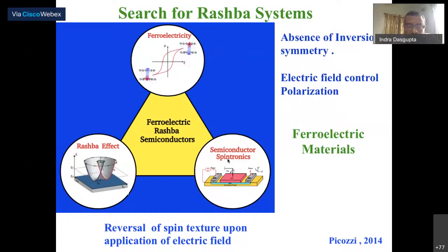The most important thing is that upon application of an electric field, you can essentially reverse the electric polarization, or ferroelectric polarization. So if the Rashba effect could be realized in such a system, then upon an application of electric field, you can essentially reverse the spin texture. This is an important thing which one needs to keep in mind: if I'm able to discover the Rashba effect in ferroelectric materials, the spin textures could be reversed upon an application of an electric field.